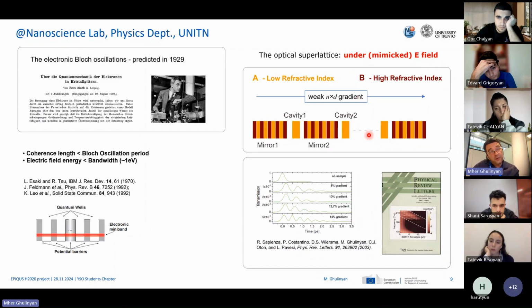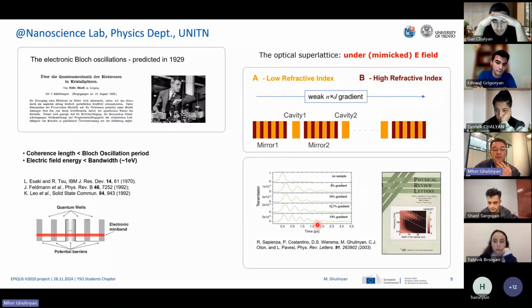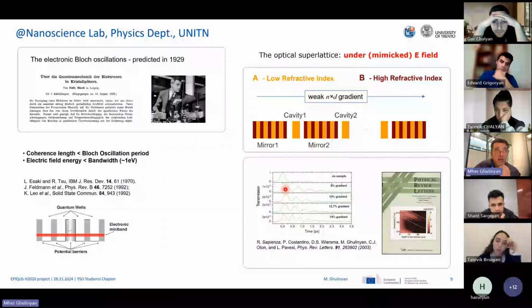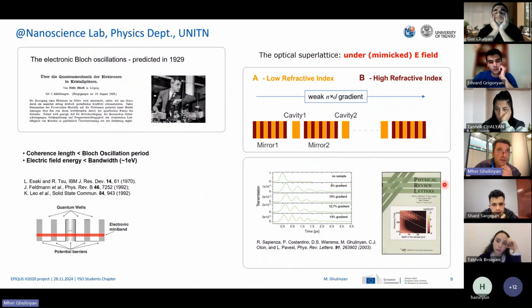Okay, and to cut it briefly, we did experiments, and we observed optical Bloch oscillations, mimicking the tilting of the bands at different gradients, so in different samples. We clearly saw that the period of the oscillation was changing. We were doing time-resolved spectroscopy and injecting a light pulse, which is the first one, let's say you see the reference one. Then we were detecting the output of the structure after some time, and we observed an oscillatory output signal in time. This was published in Physical Review Letters. We were very happy because we also went onto the cover of the journal, a big satisfaction.